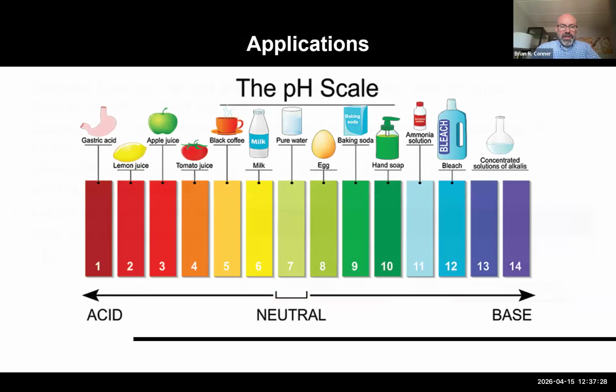So this chart gives you an idea from 1 to 13 of the sort of the fluids that enhanced coated cast iron from Charlotte Pipe can handle. And the thing that's important to note about this again is that both internally and externally, the Edge HP can handle these pH ranges, and you're not typically going to see lemon juice or tomato juice or sodas or even concentrated bleaches come in contact with the exterior of cast iron pipe. But what you may see are hot soils.